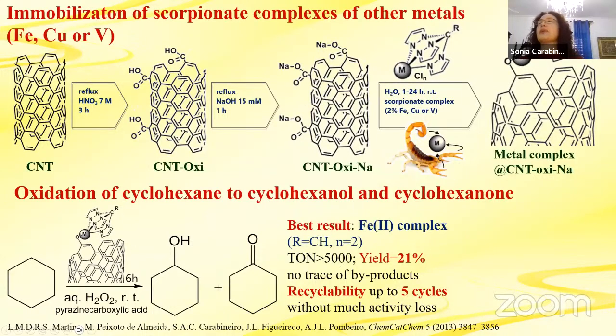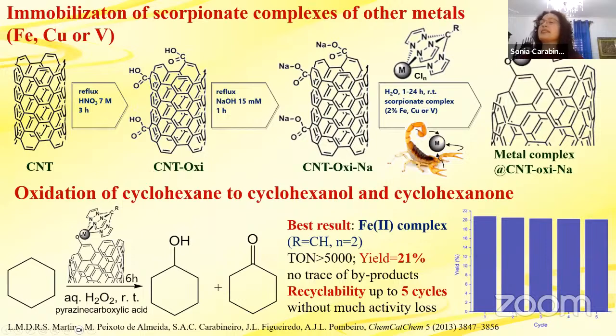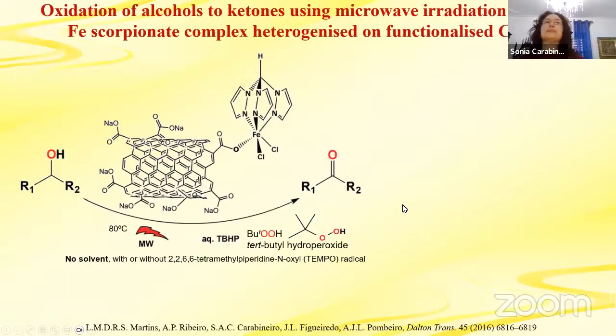So this one here, where there is an R, it was with a CH, and here 2 chlorides. Okay, so the best yield was 21%. Compared to the industrial process, it is much better, and it's also better than the 16% obtained with the scorpionates. But remember, the scorpionates did not need acid, and here we have to add a little bit of acid. And also no trace of byproducts and recyclability up to 5 cycles without much activity loss. So it was also good.